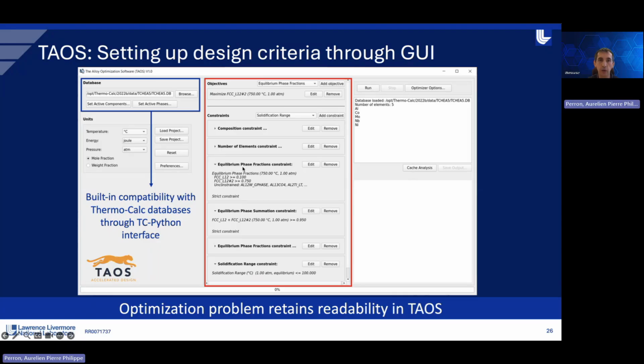So let's look at this one, the equilibrium phase fraction constraint. You can see that at 750, we pick FCC, that's the disordered one, to be above 10%, and the L12 precipitate to be above 75%. Below that, that's the phase summation that I was talking about. The sum of both should be above 95%. And if you look at the bottom, the solidification range, we want it to be below 100 degrees C. So it's really easy to save, reload your project, change your parameter, and redo the optimization.